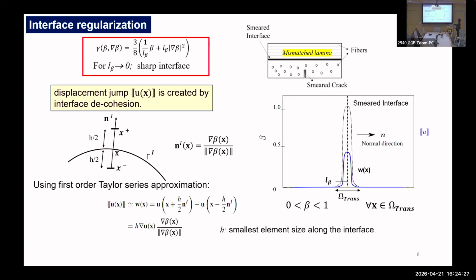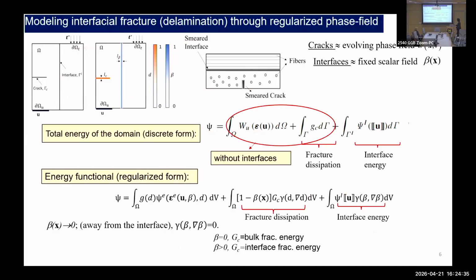So that was the interface description. In addition to that, if you remember the free energy expression from 2 slides before, I did not explain it there. The interfacial free energy classically is expressed based on a displacement jump, because, as I said, there is a displacement discontinuity along this wetting interface between 2 successive laminae. This displacement jump used to be the most important kinematical variable in the classical theory. So the free energy is expressed as a function of this displacement jump across this sharp interface.